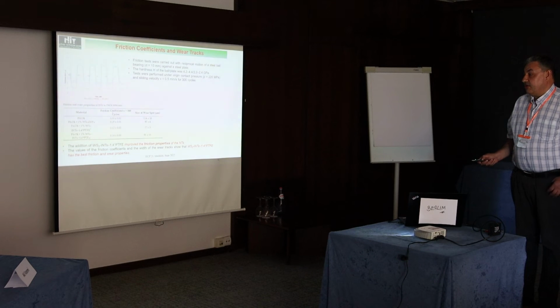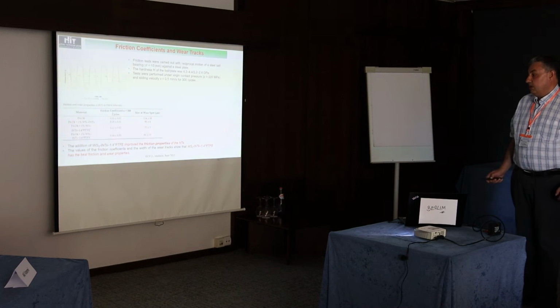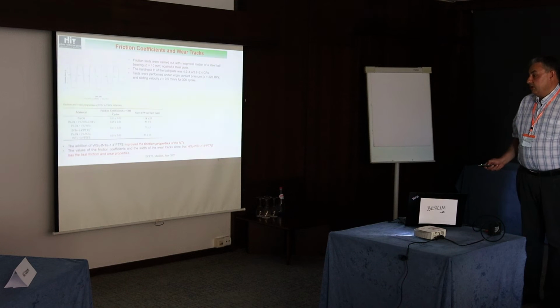When we increase the concentration of Teflon, which was not clear to us before, then the friction coefficient slightly increases, as also the size of the wear spot. So it followed that we have to use this intermediate concentration of Teflon for the best conditions.